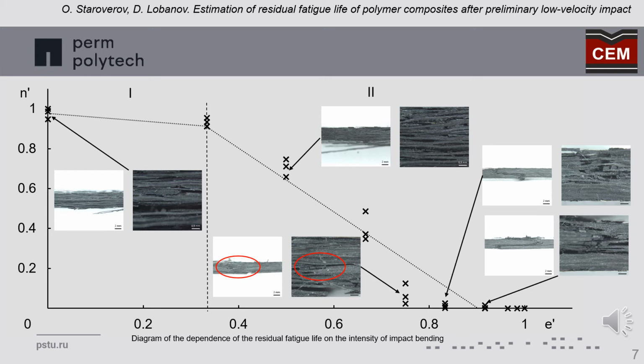Impacts with energies ranging from 0.75 to 0.90 contributed to a mixed type of fatigue failure. The photo of the destroyed samples shows the zones of fiber rupture with longitudinal cracks. This type of fracture is similar to interlayer shear.